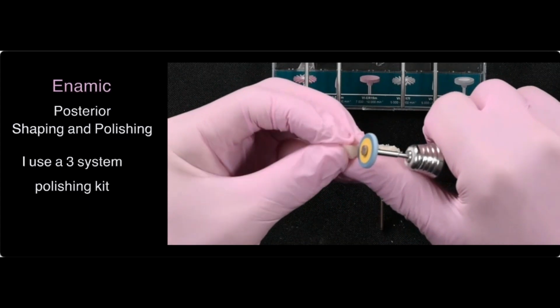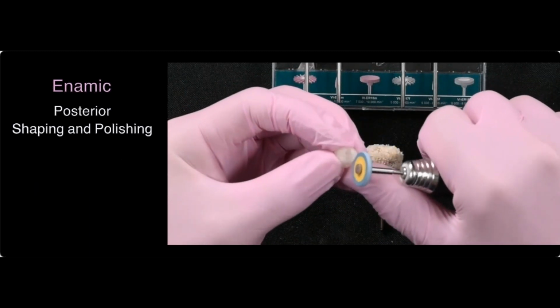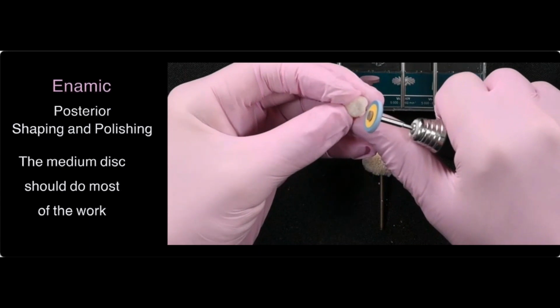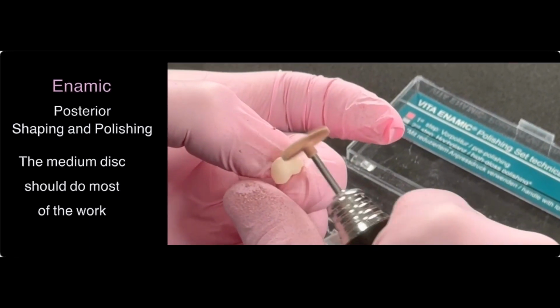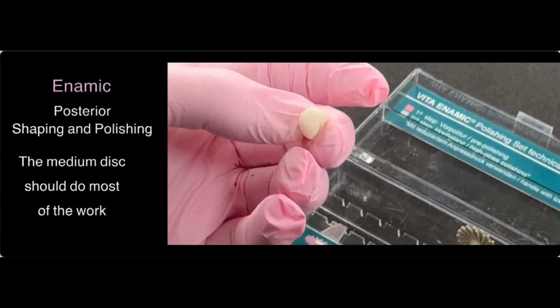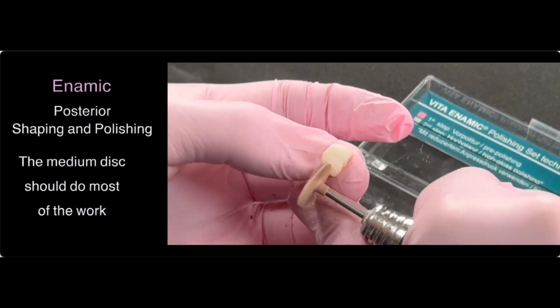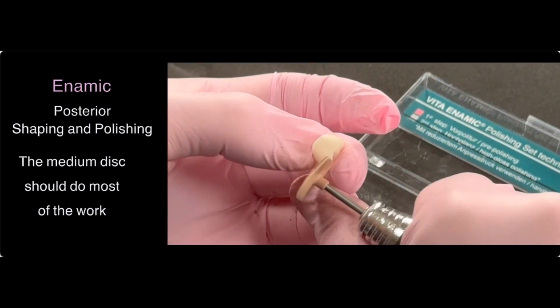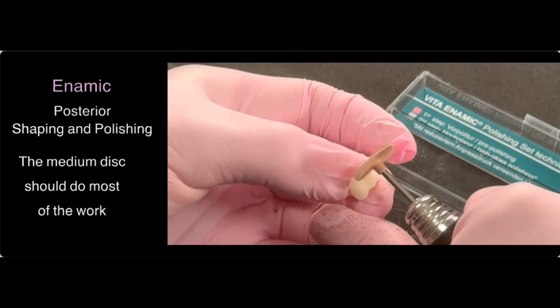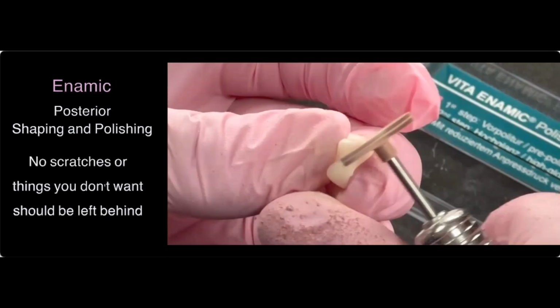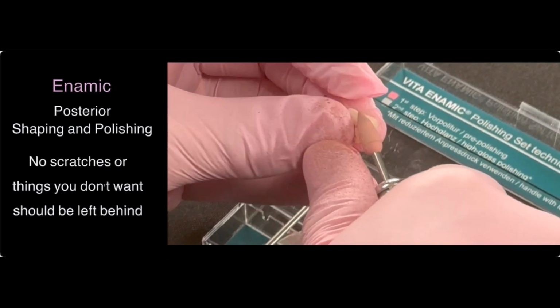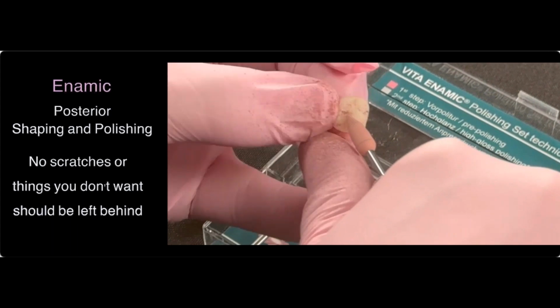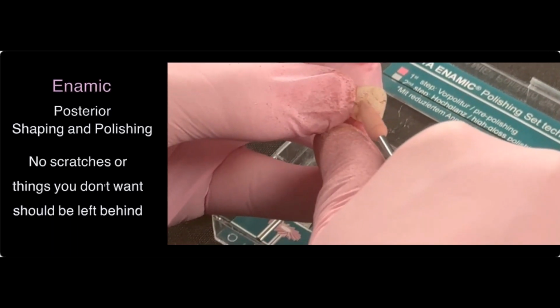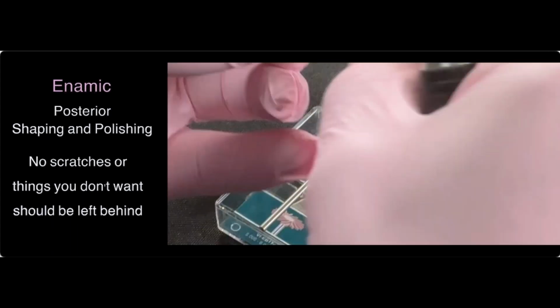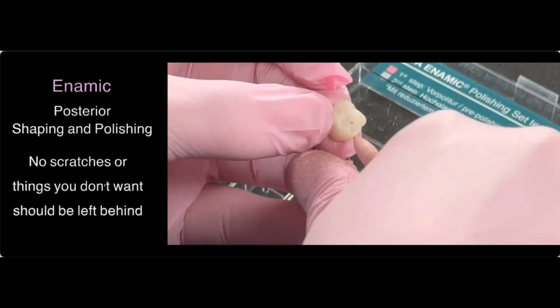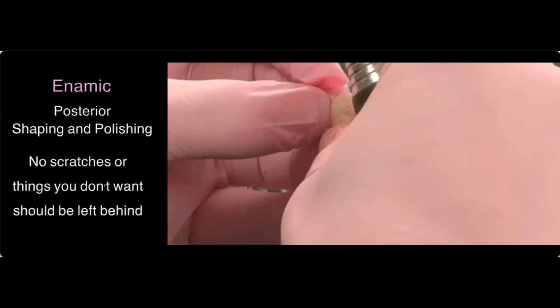And when you hand polish this material, that shine or the sheen that you will get almost never disappears. Right? Remember, this material cannot be put in the oven because it has resin inside. So we have two ways of finishing it. We can etch and silane the inside and the outside of the restorations, and then light cure glaze, which is easy, but it doesn't last as long. Eventually, after chewing and chewing, that glaze will go away because it's a resin, so it will wear off. Or you can hand polish it.